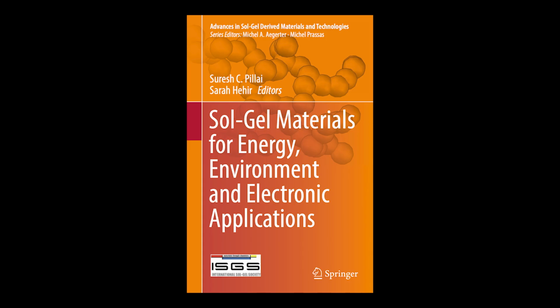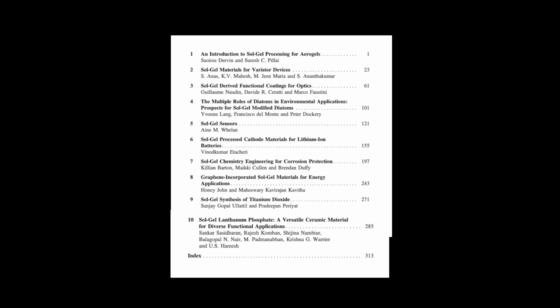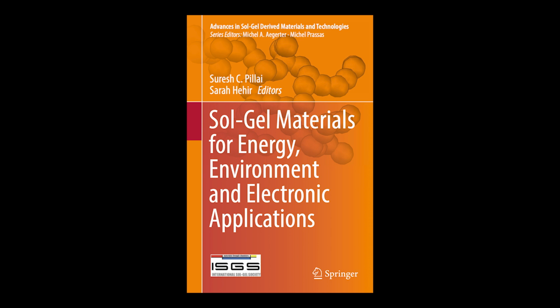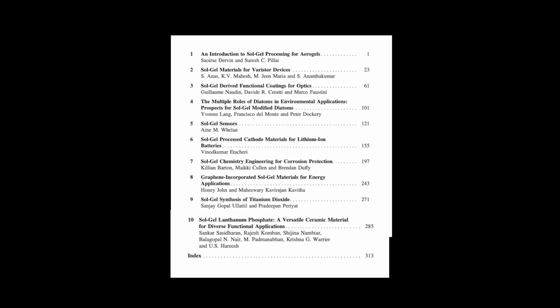So to achieve the miracle material, the aerogel, with its incredibly high porosity, we have to somehow eliminate that capillary pressure. What are the specialized methods? Right. The classic method is supercritical drying, SCD. You basically heat the solvent above its critical temperature and pressure point. At that point, there's no longer a distinct liquid-vapor interface. The solvent leaves as a supercritical fluid, completely avoiding surface tension and capillary pressure. This method produces these amazing materials with porosities reaching up to 99% and densities down to, well, 84 kilograms per cubic meter. Incredibly light. But probably expensive and complex to do at scale.